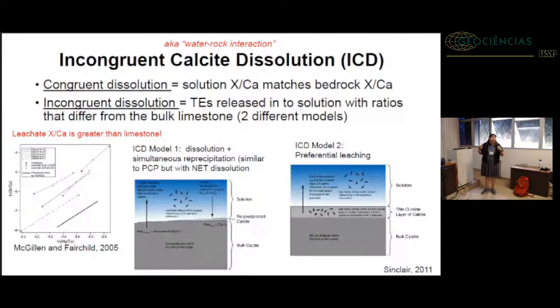But in reality, incongruent dissolution is a process that happens widely. In incongruent dissolution, the trace elements are released from the bedrock with a ratio that's different from the host rock, or from the bulk limestone. This is hard to see, but this is the natural log strontium calcium versus natural log magnesium calcium for some limestones, as well as the leachates from those rocks, showing that the leachate was always a higher concentration, higher magnesium and strontium concentration than the bedrock itself. So this was showing one type of model where there's preferential leaching of magnesium or strontium from the limestone. And that's, in Sinclair et al., model number 2. That's the easiest to understand, I think, where maybe those are sitting in sites where the bonds are more easily broken, whatever.